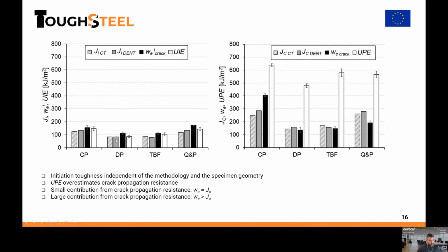In general terms, we could say that this initiation toughness is quite independent of the geometry and the testing methodology and so on. So this is good because it's easy to measure this initiation toughness. Then what happens when we look at the crack propagation resistance values, which in the end will define the full fracture behavior of this material? Well, first we can take a look at the unit propagation energy. The first noticeable thing here is that in general this unit propagation energy overestimates the crack propagation resistance a lot if we compare to the fracture toughness values JC and essential work of fracture.